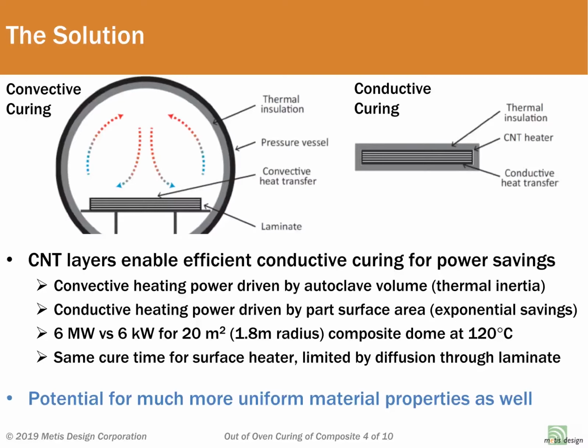inefficient. The autoclave must heat the entire volume of air inside the pressure vessel, which in turn will heat the composite part, and the large metal tool used to shape that part, which is sized to withstand the high pressure of the autoclave. Under this STTR, we developed a conductive approach to curing composites, using carbon nanotube heaters applied to one or more surfaces of the laminate. Since we are directly heating the surface of the laminate, orders of magnitude of power can be saved, which scales with the surface area rather than the volume of the part.